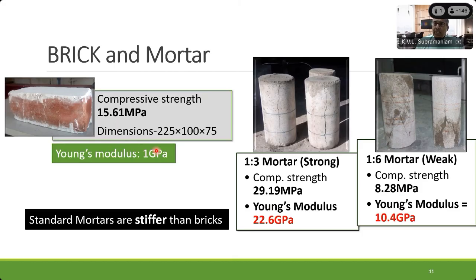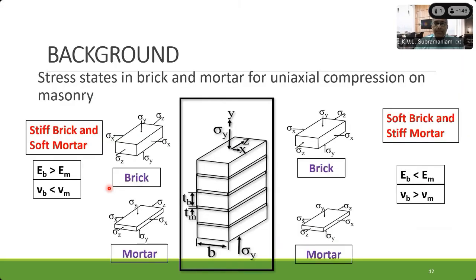And now masonry that we're making in India, the story is completely flipped. Brick is soft and the mortar is stiff. Even the so-called weak mortars are 10 times stiffer than the brick. So what changes now? If you look at the way we are taught masonry and the composite action in masonry, we typically deal with stiff brick and soft mortar. That is, the brick is much stiffer than the mortar.